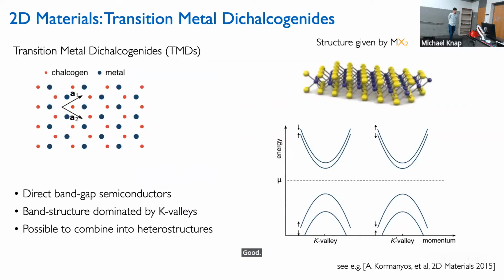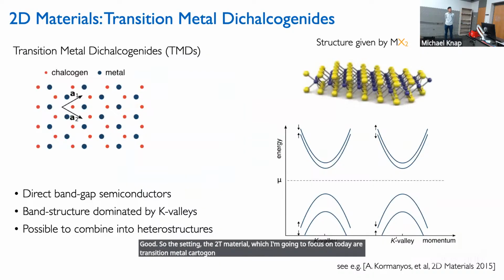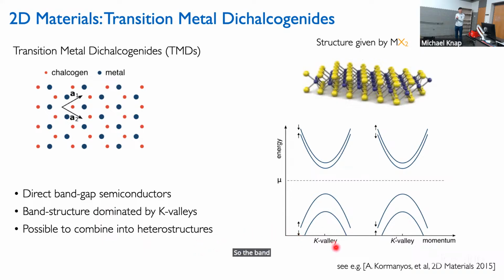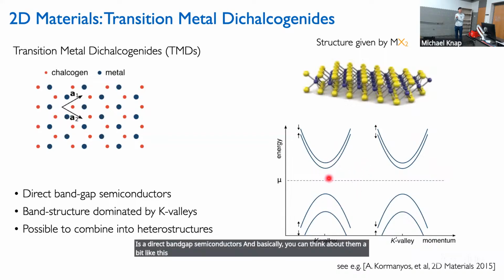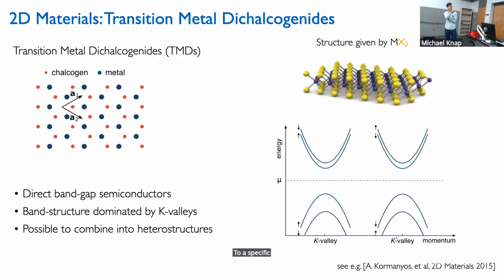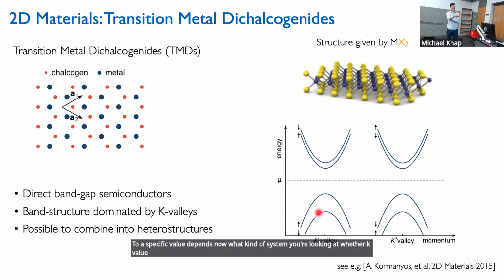Good. So the 2D materials which I'm going to focus on today are transition metal dichalcogenides, TMDs. These materials have a honeycomb structure, but in contrast to graphene, they have a broken inversion symmetry. So the band structure is still dominated by the K and K prime points, but it's not linear, it's gapped. These are direct band gap semiconductors, and basically you can think about them like this: parabolic band structures dominated by K and K prime valleys. In particular, there's also a so-called spin momentum locking. As you can see here, the spin of the band is fixed in these materials to a specific value. It depends on what kind of system you're looking at, whether at the K valley the valence band is spin up, or the other way around. Okay, but this is known.